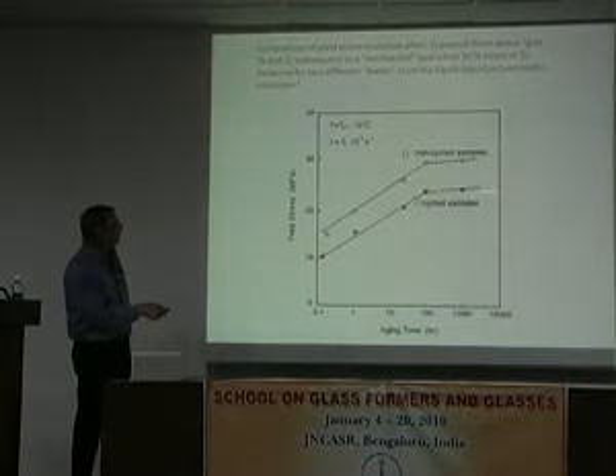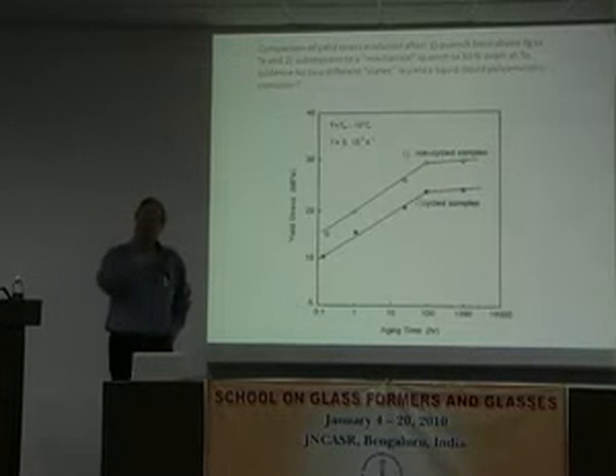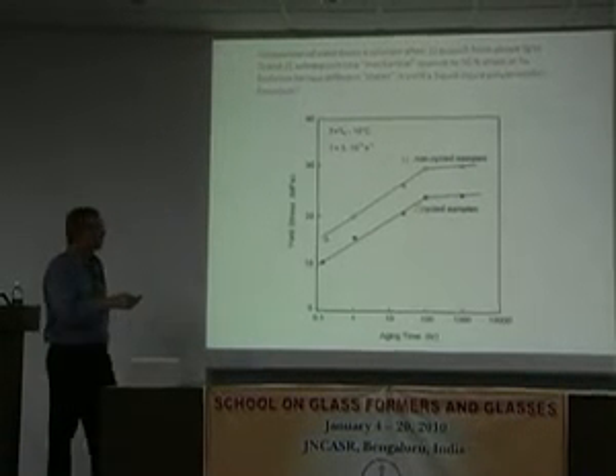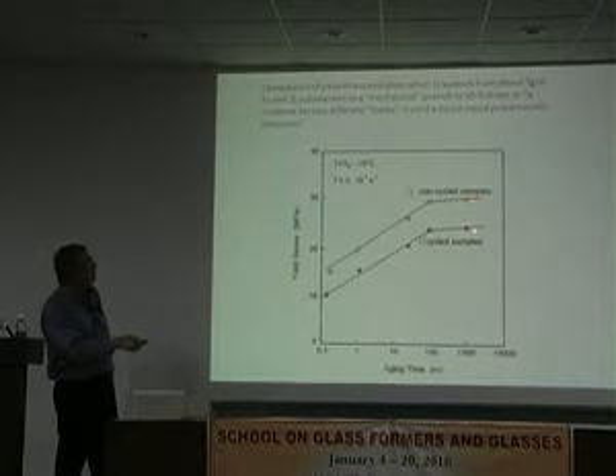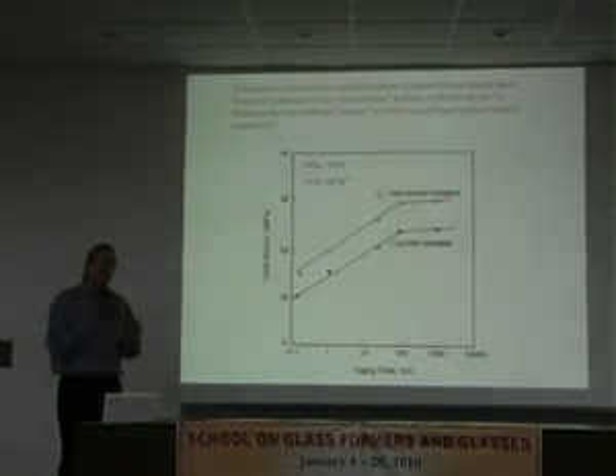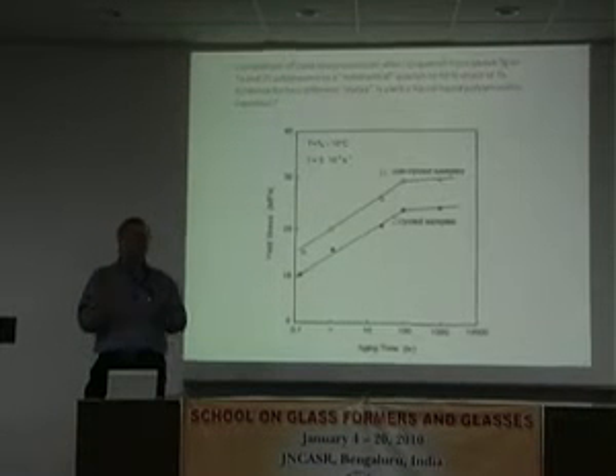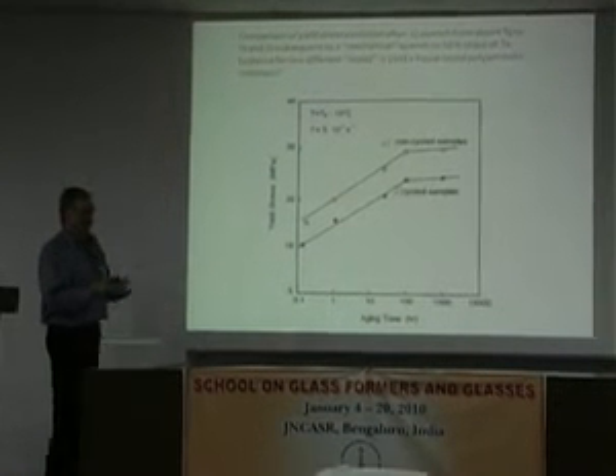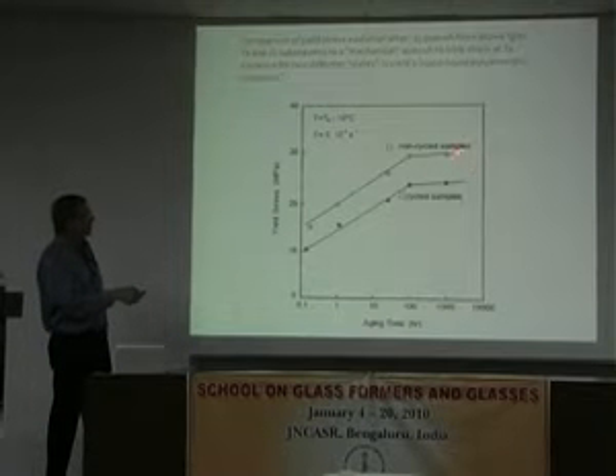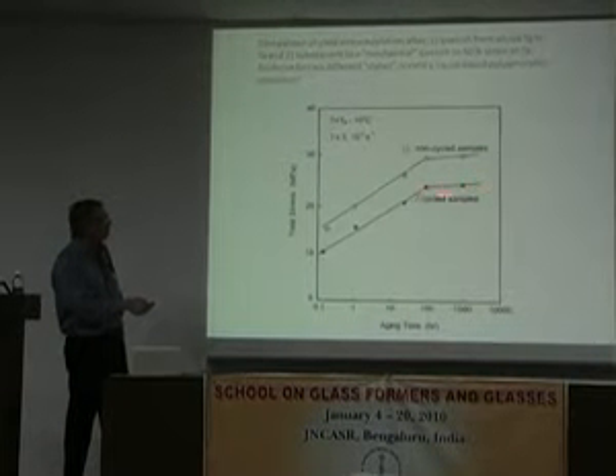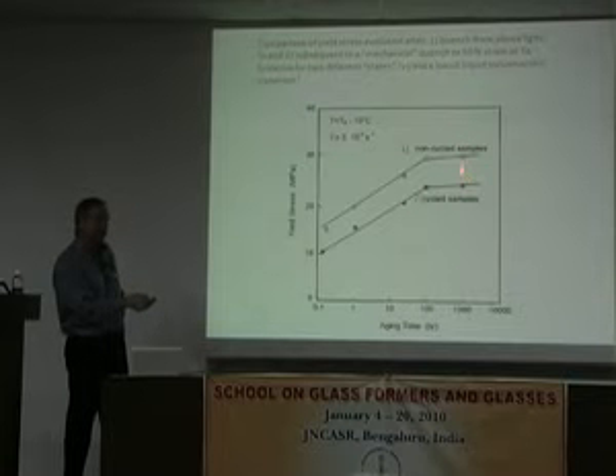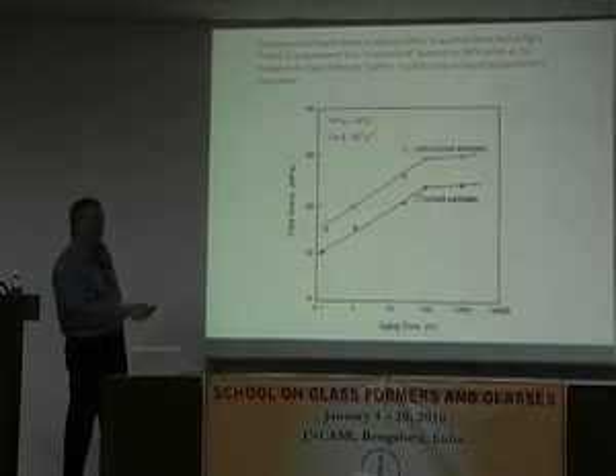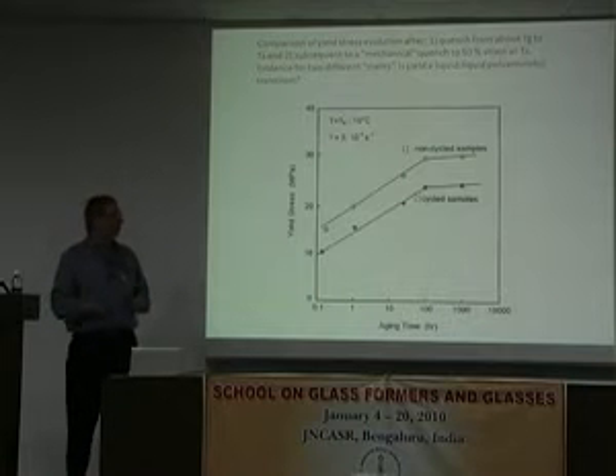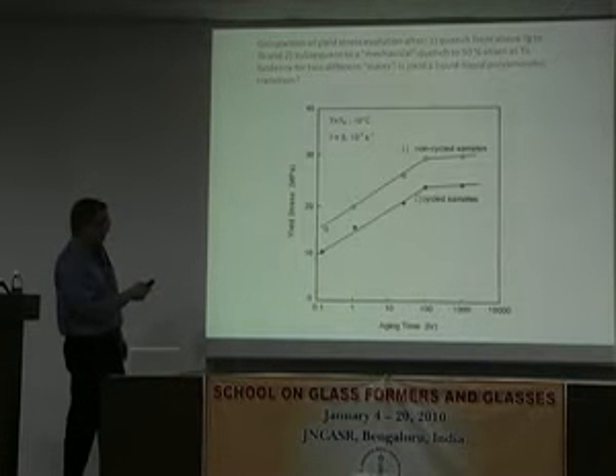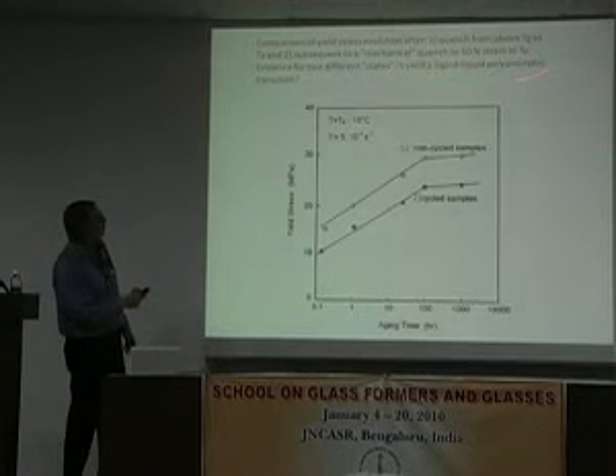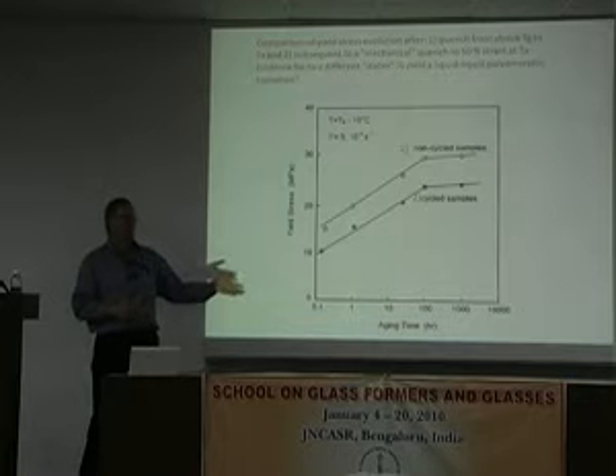But where it levels off, now we could go out further. There's always a question when we stop these experiments. But it certainly seems to be stopping at a different place. So this is why the yield, and some people actually treat yield as a phase transition. Whether you like that or not is a different question. But this looks like we've come to a place where the mechanical response is different in the two cases. And it's not just a little bit different, it's quite a bit different. So we were very surprised, and the question we asked was, is there some sort of polyamorphic kind of transition here between one amorphous state and another?